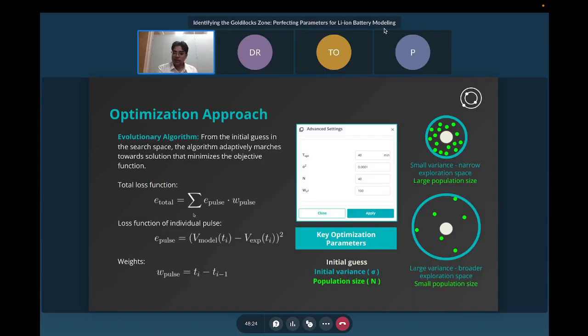For the optimization process, if you have some idea on these parameters, you can start with an initial guess which is closer to what you would expect. In that case, you have a higher chance of hitting the optimal solution. But what often happens is that for a given cell, you have no idea whatsoever of what these parameters could be. And in those cases, it is also extremely difficult to come up with an initial guess which is close enough to what the order of parameters might be.